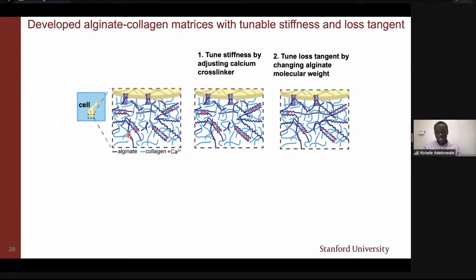So I know that this loss tangent is a new term that I introduced. It's essentially a ratio of the loss modulus to the elastic modulus, and it's a measure of the viscosity in the material.